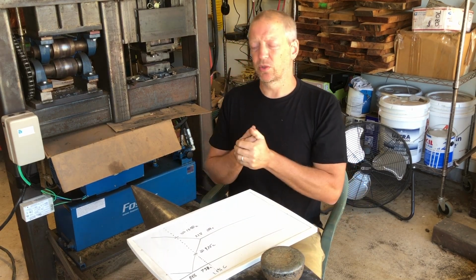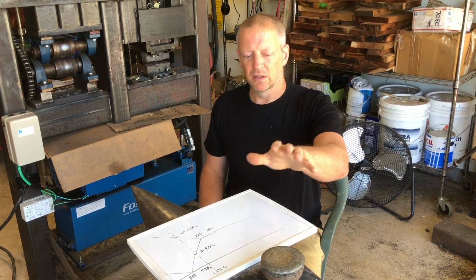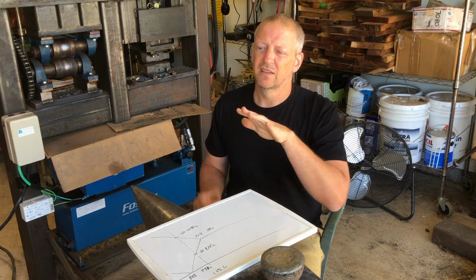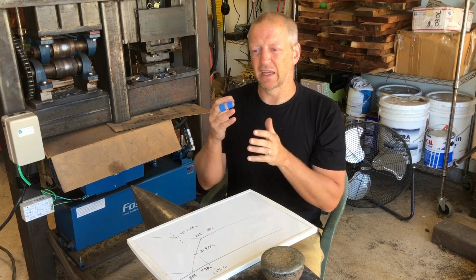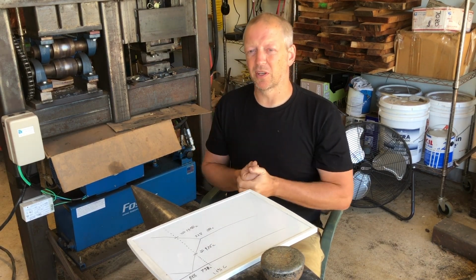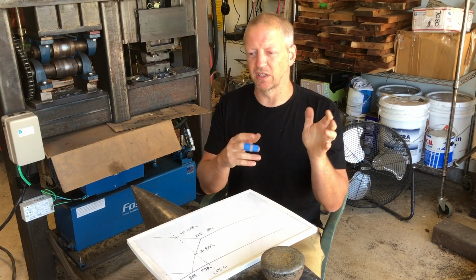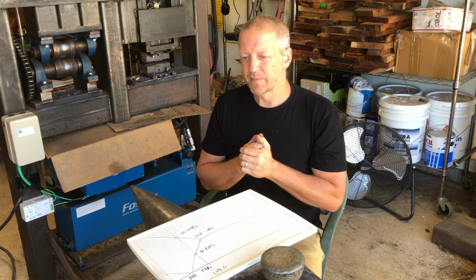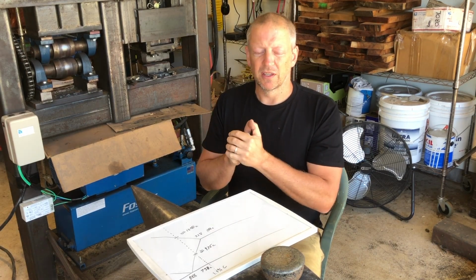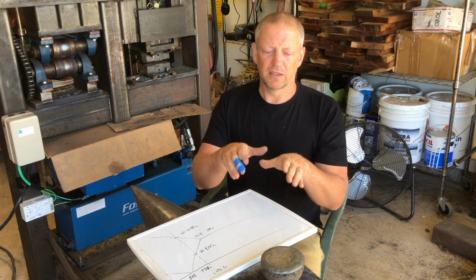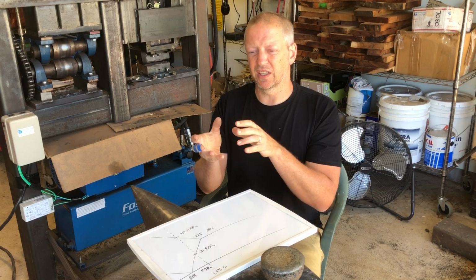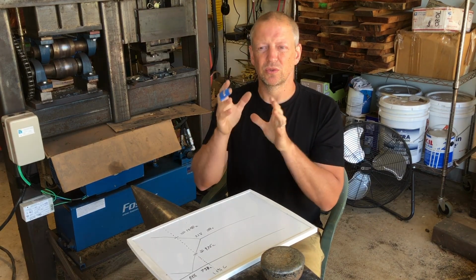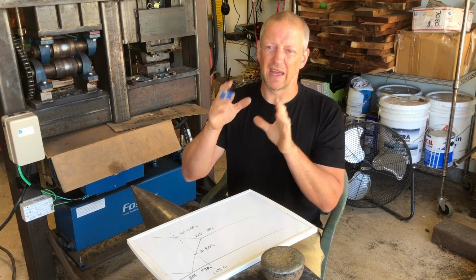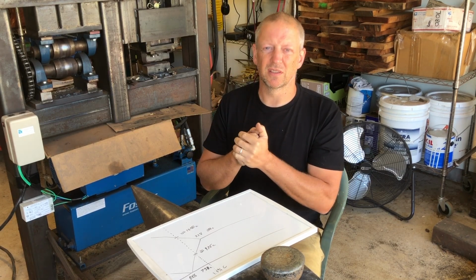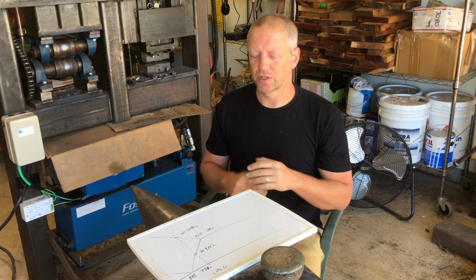For most modern smiths who are making crucible steels, the chemistry of the ingots and the cooling rate of the ingots is probably going to be a bit more consistent than you would have seen historically. So, to a greater degree, you can establish a set protocol of, I'm going to take my ingot and treat it in this fashion, every time. And that gives me the same starting structure when I go to forge.